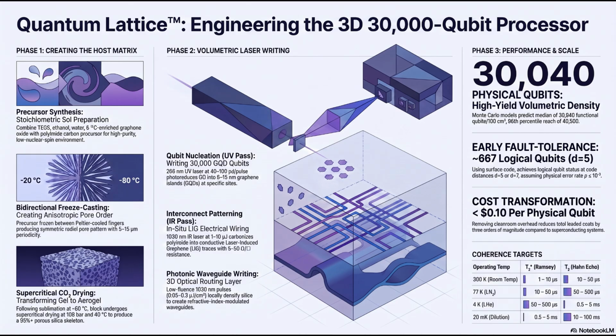Yeah. What were the dice that were rolling? What are the ways a single qubit site can fail in this manufacturing process? They modeled 4 distinct failure modes as independent Bernoulli trials, meaning each site either passes or fails based on specific odds. First, a GQD nucleation miss. There is an 8% chance that the UV photon hits the pore wall at a weird angle and fails to cleanly sever the oxygen bonds, meaning the quantum dot doesn't form correctly. Okay, so 8% chance the dot just doesn't print.